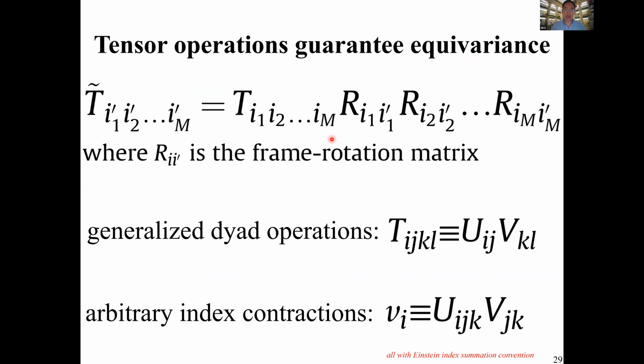What it says is that pretty much every physically well-defined quantity should be represented as tensors. When you undergo a rotational transform, it must transform by this particular tensor contraction law. In other words, when you tilt your head and you measure the same physical quantity, the numbers would change, but it should still be the same physical quantity, and therefore it must satisfy this relation when you undergo a frame rotation. So as long as you just follow this tensor Einstein notation, you can construct a rank 4 tensor by doing a generalized dyad of 2 rank 2 tensors. Or if you do, let's say, dummy index summation, you contract a rank 3 tensor with a rank 2 tensor, you get a vector. So basically, as long as you follow the Einstein index summation convention, you're guaranteed to have equivariance.